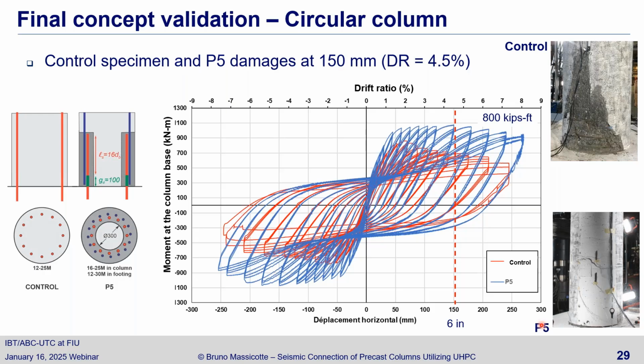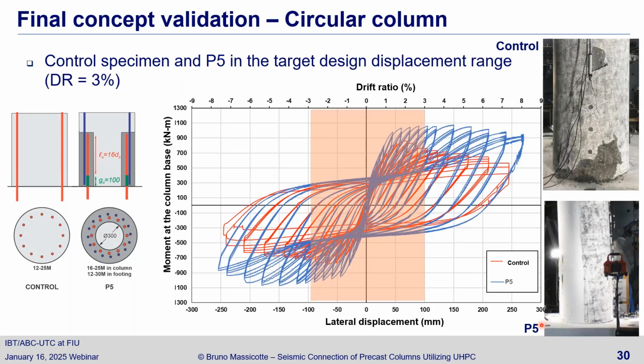And if you look at the usual range for which you would be designing a column, and compare the damage between the control column and the precast one, there's no damage in the precast one. So it means that after a very severe earthquake, for this column at least, if you carefully do your design, you will end up with no apparent damage, no crushing, no spalling in your precast element, and you will be concentrating all the plasticity and damage, with very stable behavior, into the plastic hinge region, hidden, and so you will have a column that won't need repair.